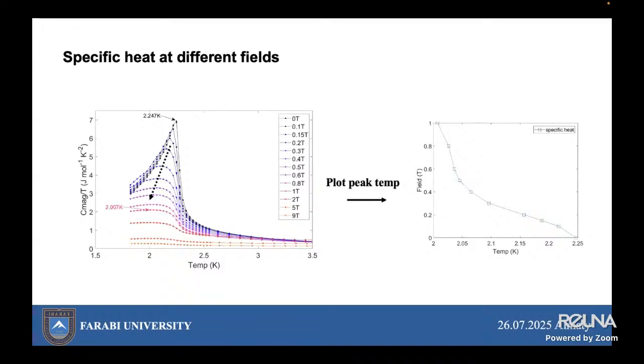And next slide, on this slide, they give the results of the specific heat at different magnetic fields. You know that the magnetic specific heat of terbium tantalate at selected fields shows, at the Néel temperature, a sharp peak. This corresponds to the 3D antiferromagnetic ordering seen in the differential magnetic susceptibility versus temperature plot. On application of magnetic fields, the peak decreases in temperature and becomes broader, differing from the magnetic susceptibility and isothermal magnetization measurements. The second Néel temperature wasn't seen in the heat capacity data, possibly due to the change in magnetic entropy being too small to detect and insufficient temperature steps, resulting in the merger of the first and second Néel temperatures.